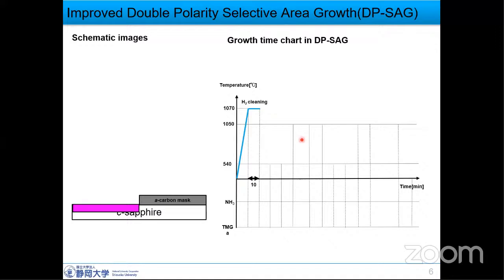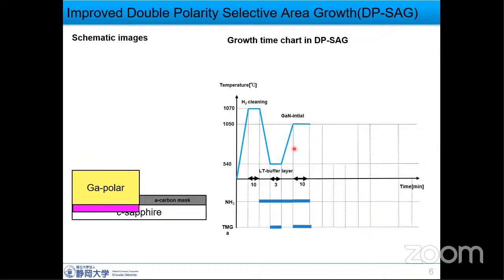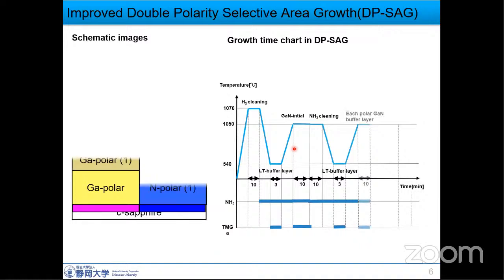The temperature was lowered to grow the low temperature buffer layer for gallium polar. Then the temperature was raised to grow the gallium polar initial layer. After growth, the carbon mask was removed to fabricate nitrogen polar gallium nitride. Ammonia cleaning was treated. The temperature was lowered for the low temperature buffer layer for nitrogen polar. Then the temperature was raised. After raising the temperature, each polar gallium nitride buffer layer was grown. Then the double polarity selective area growth was performed.